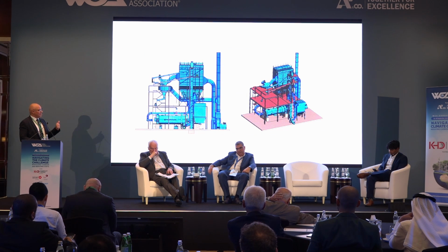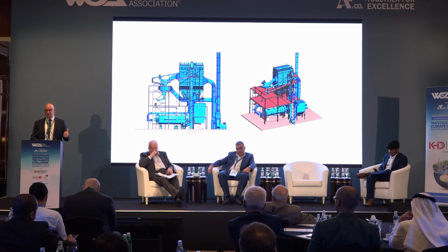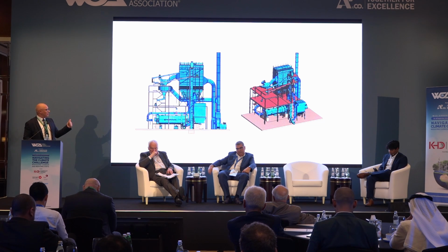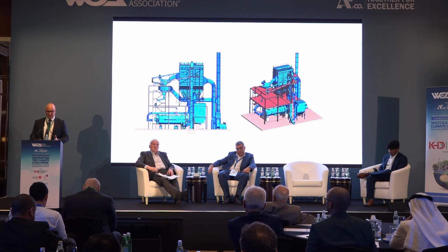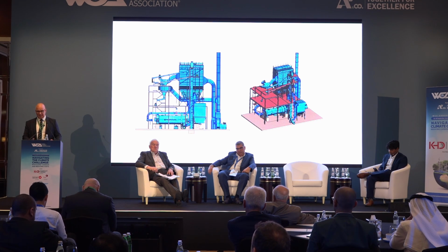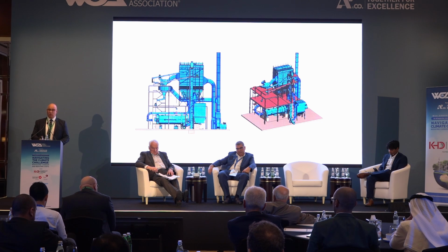A second case is a plant in Central America. This plant had a third generation separator. And here is where I'm saying how important small things are. Third generation separator, but what happened is that most of the plants done in the last 30, 40 years with this third generation separator were calculated for not such high Blaine cements. So the circulation factor was changing, the recipes were changing, the moisture was changing, everything was changing. The separators have a different relation between feed and final product.